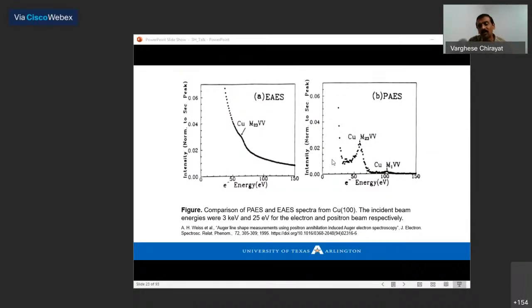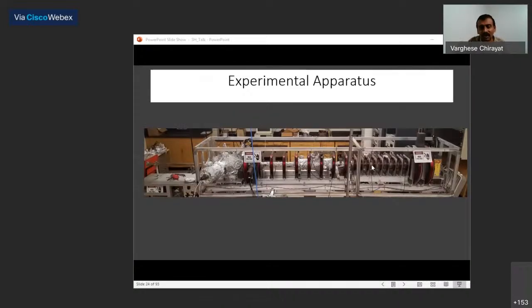Okay, and there you go. I'll show you the removal of the secondary electron background. On the left side is the same spectra that I showed earlier. You hardly see a bump of the copper MVV Auger peak, but when you use positron annihilation induced Auger electron spectroscopy, you can come in with energy less than this. In this specific case, I have come in with energy at 25 eV, and hence your secondary background is much removed from the actual Auger peak, and you can clearly see it. Not only the M23VV, there is also an M1VV, but we will not go into the details of that now. In this specific case I have come in with 25, but you can come in as well with 1 eV.